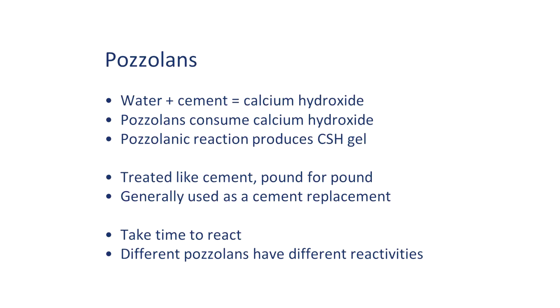One thing to keep in mind is that pozzolans take time to react, and different pozzolans can react much faster than others. Most of them react quite slowly. The different chemistries give you different reactivities, as well as the temperature you're curing it at and whatnot. To give you a rough idea, I'm going to jump ahead: you don't even start to see any strength gain from VCAS. This is based on my tests done on cylinders for at least a week, maybe more.